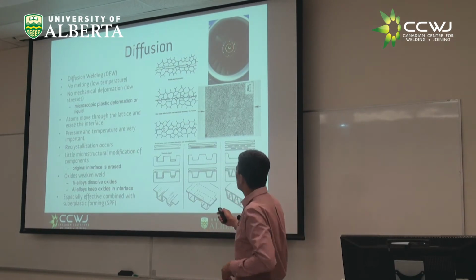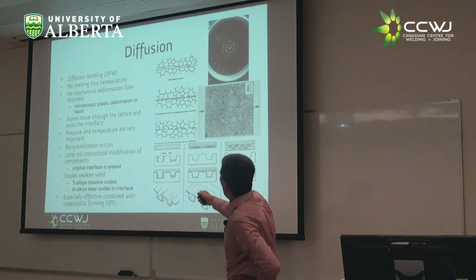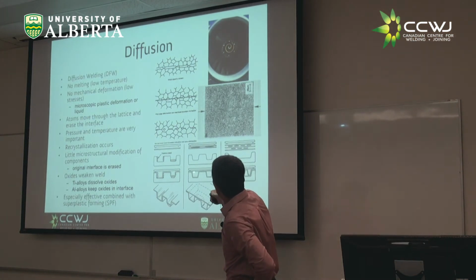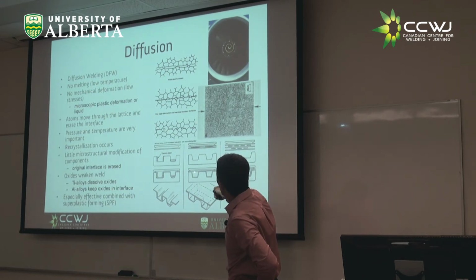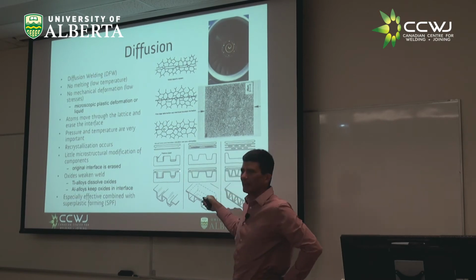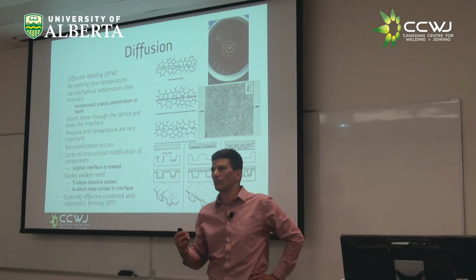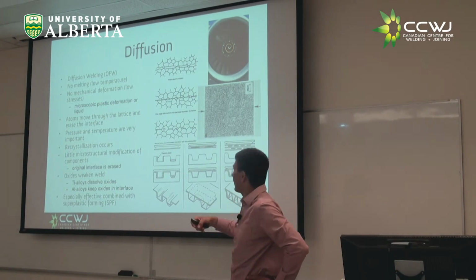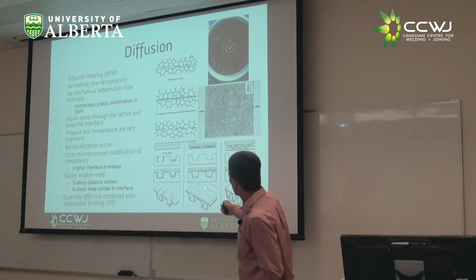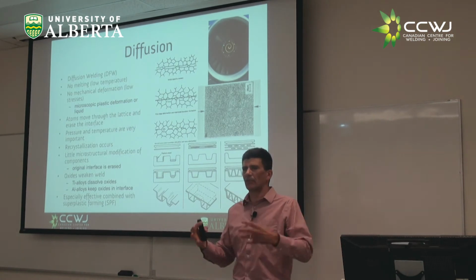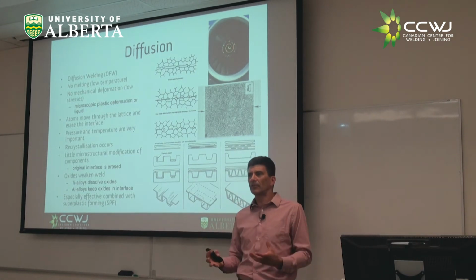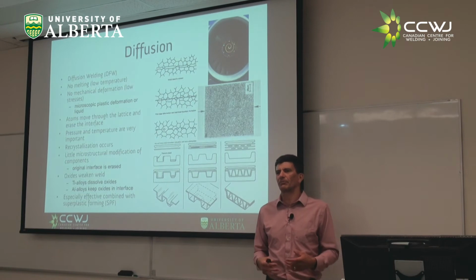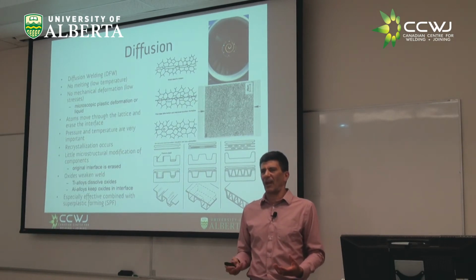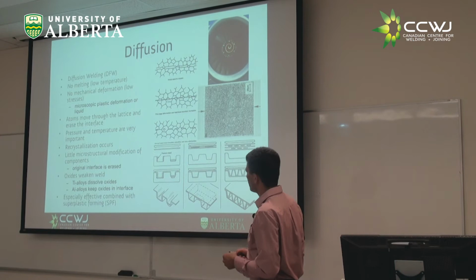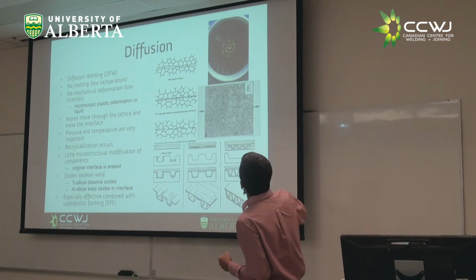And you can make structures like this in which you put two pieces of titanium together with something that separates them. You heat it up, you blow gas in there, an inert gas. You don't want to be blowing anything with oxygen. And if it is hot, it's going to start with superplastic flow. And eventually, you're going to make a 3D structure that is very stiff, very light, and relatively cheap to make, right? Because of superplastic forming and because of this property of titanium.